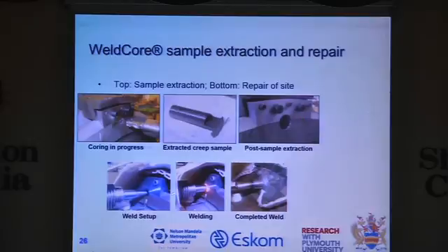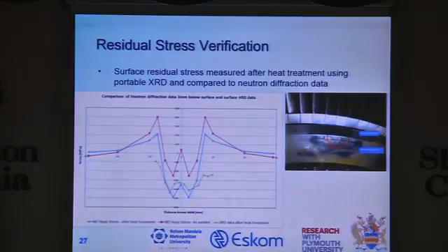That's the extracted hole, and what you're seeing here is the repair process. Interesting here are the residual stresses that we measured. Because we're very careful, we did residual stresses on the repair side, blades put back, by XRD on the surface there. Now look at the neutron data, the red and the blue, and then the green line here is our XRD data. That gives you confidence. You've now done a repair, and your residual stresses on the surface are more or less what you saw in your experimental work and your samples, so confidence is high, and you carry on.